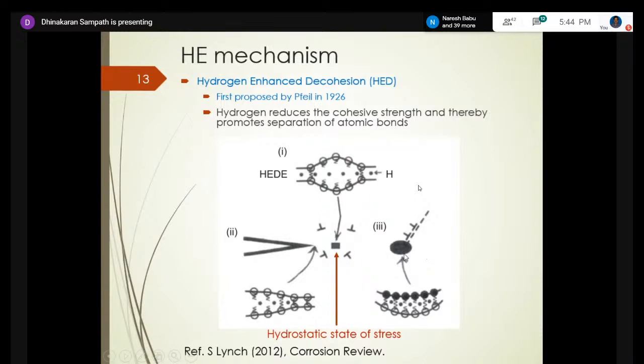And in the case of some obstacles, some second phase particles, when dislocations create a stress rise there, a stress concentration or stress intensity, hydrogen goes there, and again, at the interface of second phase atoms and matrix atoms, because of the hydrogen, it just unzips and leads to a crack. So this is the very early model. This is not experimentally proved, because one has to see at the atomic scale; only simulations are there.